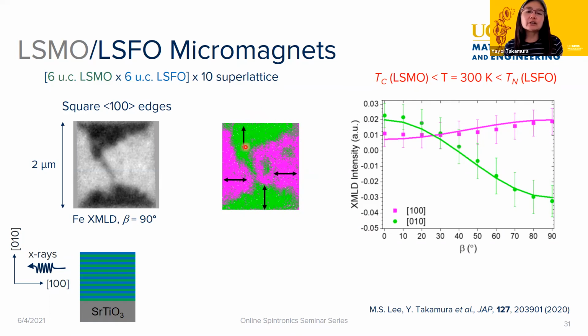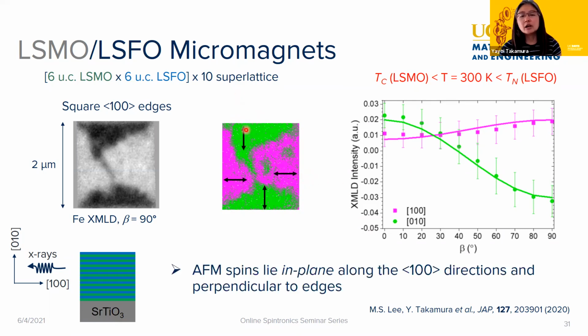And interestingly enough, these domains are such that they always want to be perpendicular to the edges of the nanostructures. They want to lie along the 1, 0, 0 directions. And what's also different from the thin films is these are now completely in plane. There's no canting angle for them. So somehow the in plane or thin film nature pins these antiferromagnetic planes to lie completely in plane.